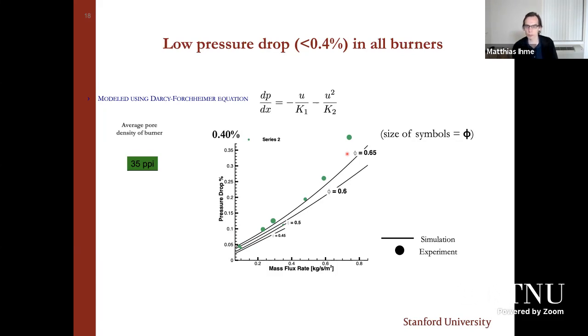Just to give you a reference point, for typical gas turbine combustion applications we're talking about pressure drops of about 3%. So this porous media burner is well below this stability limit. And for different operating conditions, you're seeing that we are falling underneath this Darcy-Forchheimer relation, meaning overall there are very acceptable pressure drops, meaning that this is not a performance limitation for this practical